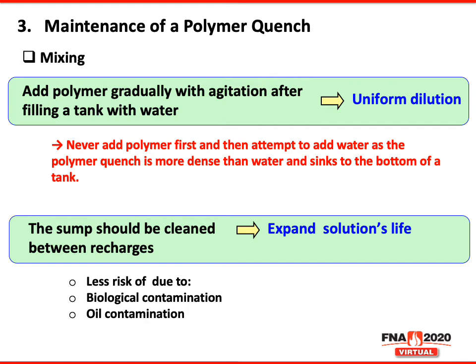So how do you mix up a polymer? Well, polymers are more dense. They're heavier than water. So you don't want to put the polymer in first and then put the water in on top of it, because then it requires a lot of shear and agitation to get that polymer to mix. Notice I use the word shear. You're going to have to shear that polymer, which we showed already is a bad thing because it changes the viscosity of the polymer and it changes the cooling properties.